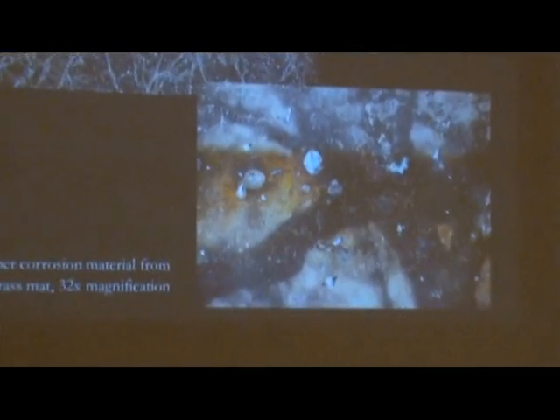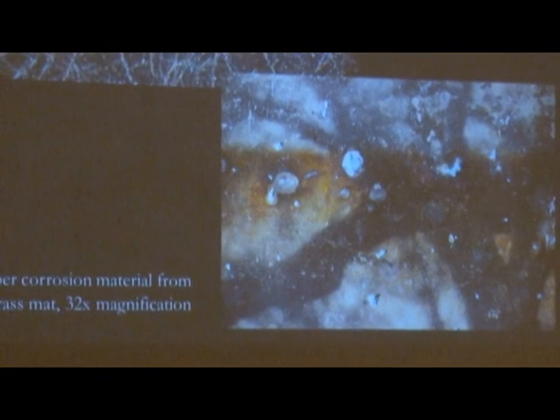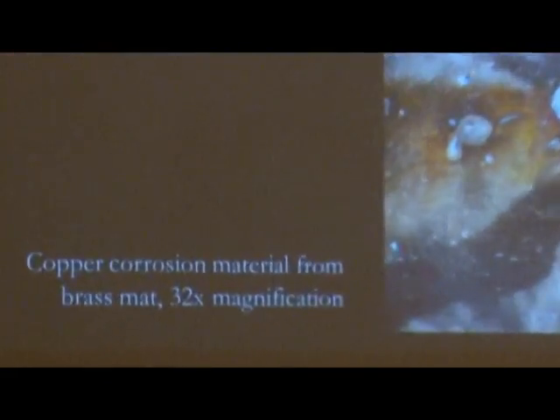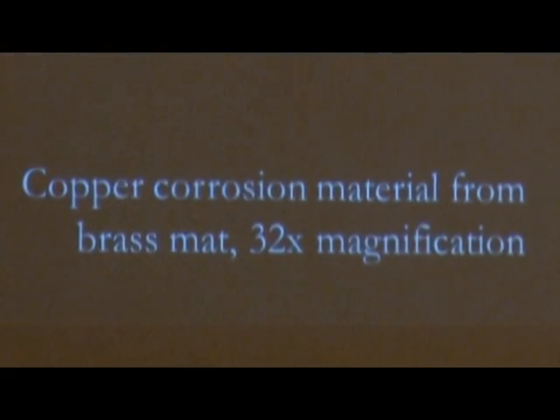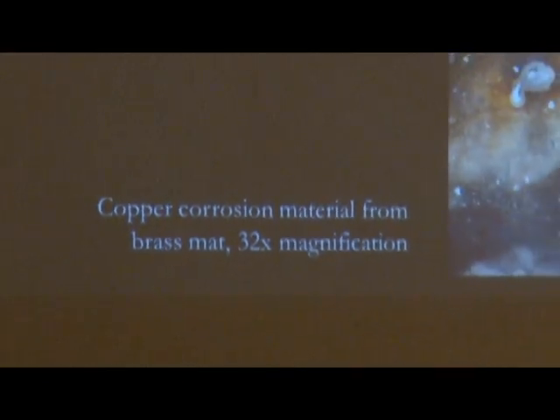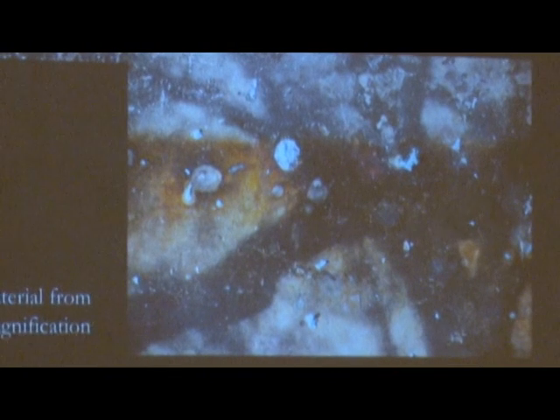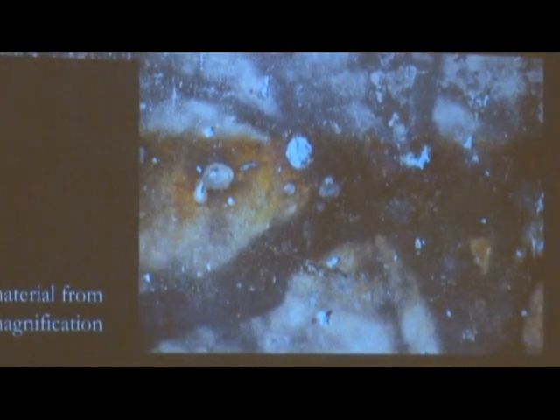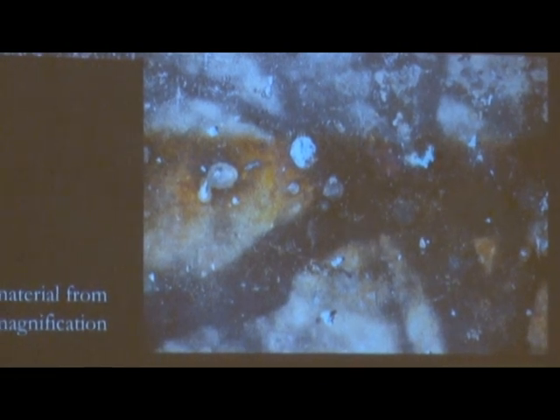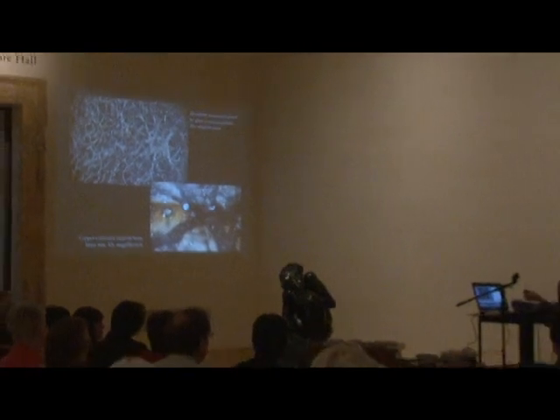And what you see in the bottom is the corrosion of the daguerreotype triggered by brass mat. Since brass mat is in direct contact with the plate, it inherently interacts with the silver surface. Also, it corrodes, so you would think brass does not corrode, but given the right or wrong condition, it can corrode and it can drop the corrosion material on the plate, and that starts to interact with the silver surface in its own way.